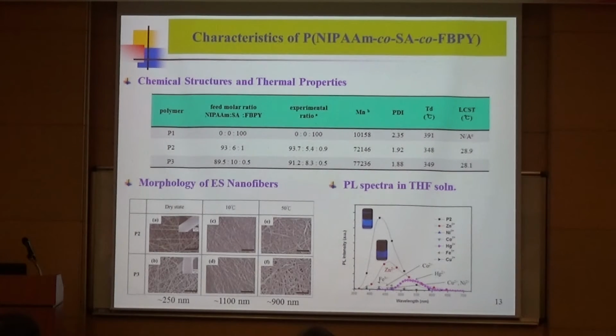Okay, so here we prepare three random copolymers with different compositions. This table shows the chemical structure and the thermal properties. The SEM images show the morphology of these electrospun nanofibers in different states. For the as-spun nanofiber, the average diameter was around 250 nanometers, and after immersion in aqueous solution, it can retain the fibrous conformation with good swelling of water to a larger diameter, around 1 micron.